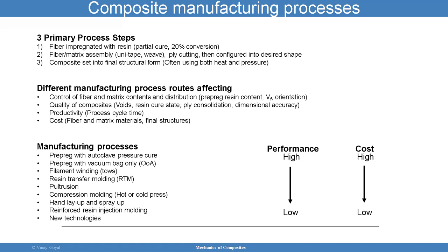Different manufacturing processes can be used. And you have control of fiber and matrix contents, so I can control the amount of resin content, and depending upon the amount of resin content, the quality of the product is affected. And these different manufacturing process routes can also affect the quality of the composite, like voids. You could have voids within the composite. Voids may not be a good thing. If I have voids within a composite, within the resin, then those act like stress concentrations. And those stress concentrations can then affect the performance of the composite.